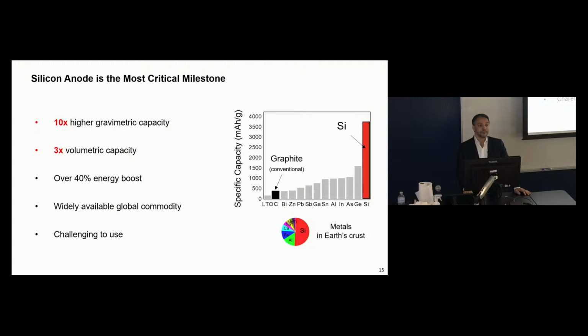As I mentioned, the development of a high-performance silicon anode is the most critical milestone. It has about 10 times higher gravimetric capacity compared to intercalation-type graphite. It has about 3 times higher volumetric capacity at the cell level for the same cathode, the same separator, foils, and so forth. It provides over 40% energy boost. It is also widely, globally available. There is as much silicon in the earth's crust as all other metals and semi-metals combined. It comes from sand. The only problem is that it is challenging to use. It is challenging to stabilize.